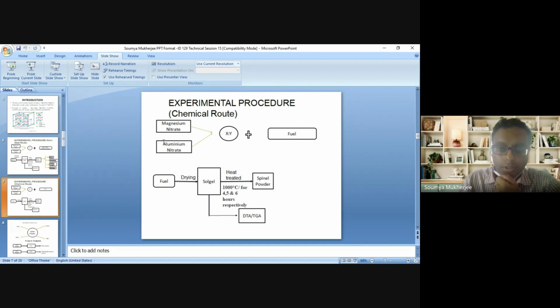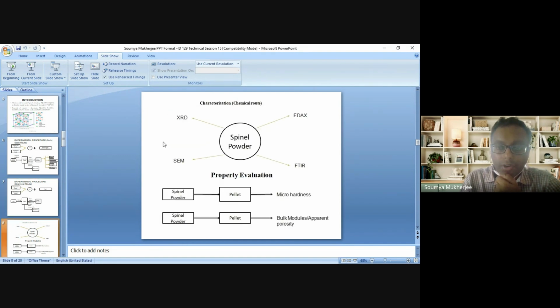In this case, after doing thermal analysis, we have heat treated at 1000 degrees Celsius for 4, 5, and 6 hours durations. It is followed by characterization in terms of XRD, SEM, EDAX, and FTIR, and property analysis, the microhardness or bulk modulus and apparent porosity calculations.